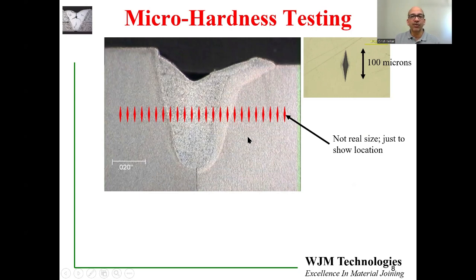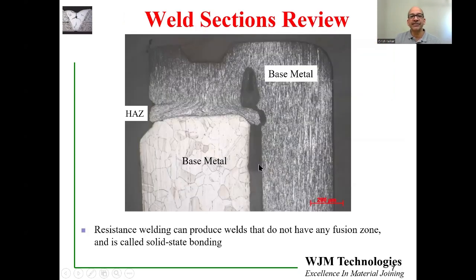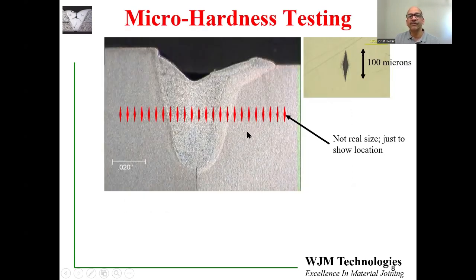Now this weld is a butt weld where the two parts have been pushed together and made a weld. And you can see that it is a partial penetration weld because we haven't completely gone down the interface. So if this weld were to be flexed, this could become a high stress point and the crack could start growing over here. Now, if this weld was brittle, then the crack would easily propagate and go through the weld to failure. So one of the most important aspects that we want to understand, in addition to the metallurgy, in addition to the size and shape of the grains and different zones and so on, is the mechanical behavior of the weld, and that we can get by micro-hardness testing.